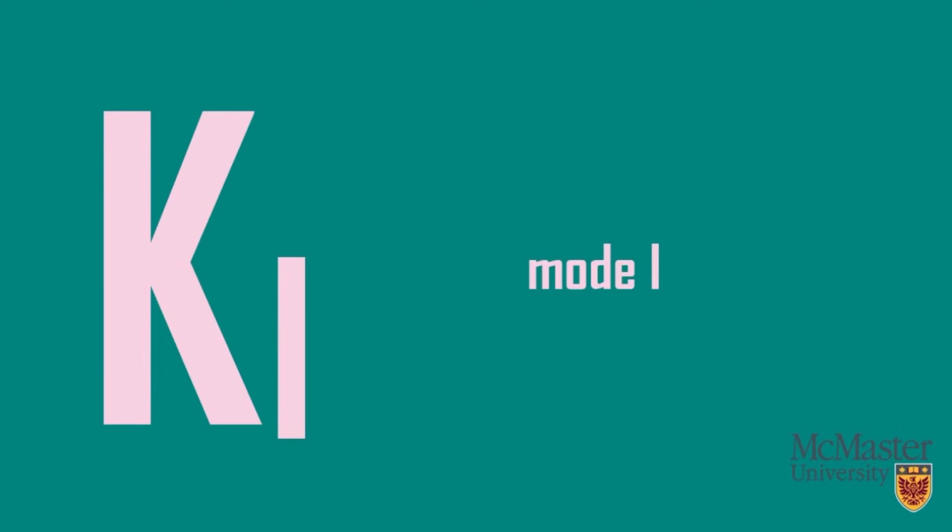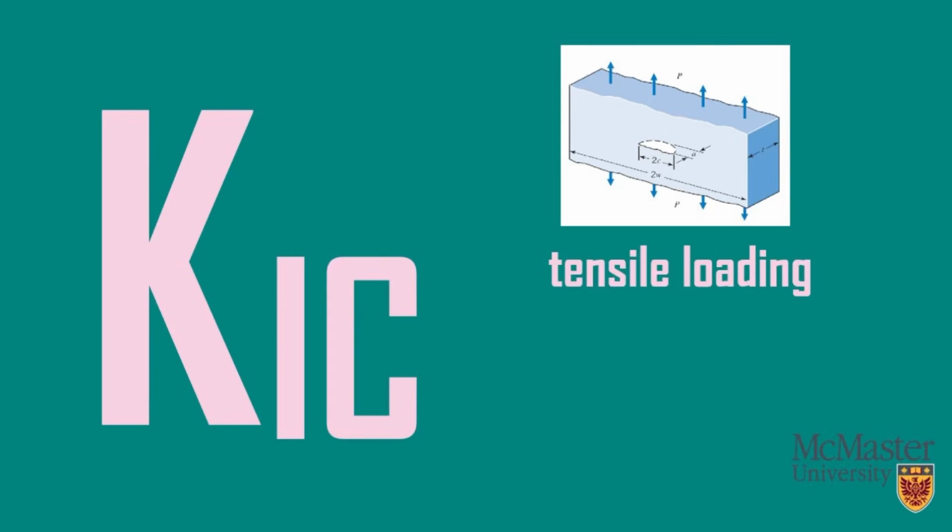Most currently available values of K and Kc are for tensile loading, which is called mode 1. Accordingly, these values are designated as KI and KIc. The material is roughly in a plane strain state. Most of the available values of KIc are applicable to relatively thick members. However, the crack root material in a sufficiently thin member provides a plane stress condition, and the KIc value of plane strain is much lower than that of plane stress. Therefore, when the thickness is unknown, the KIc plane strain value that is easier to obtain is useful for conservative calculation.